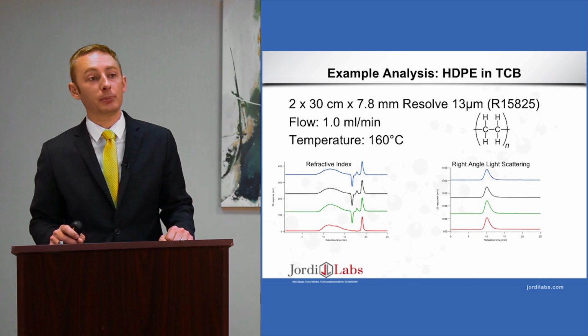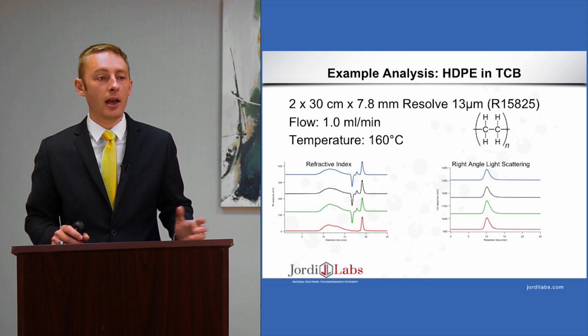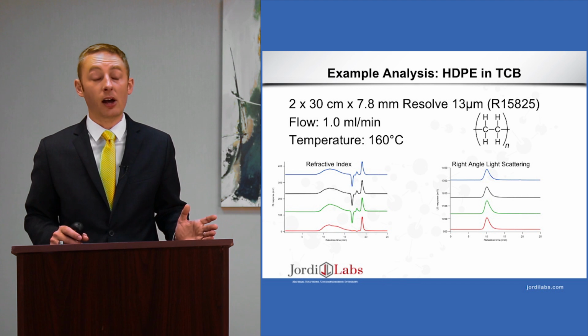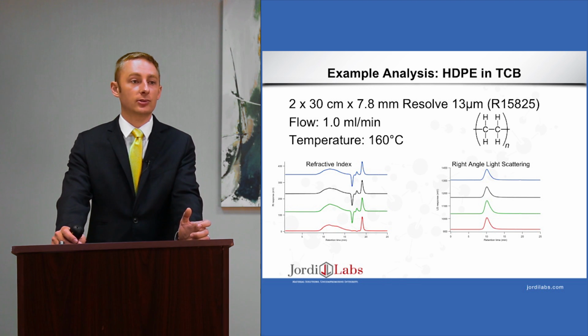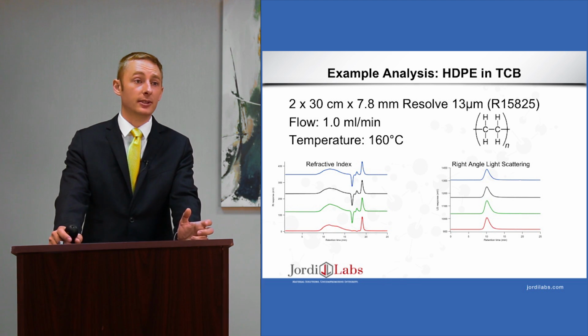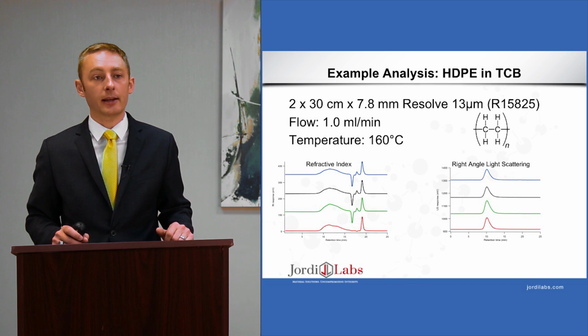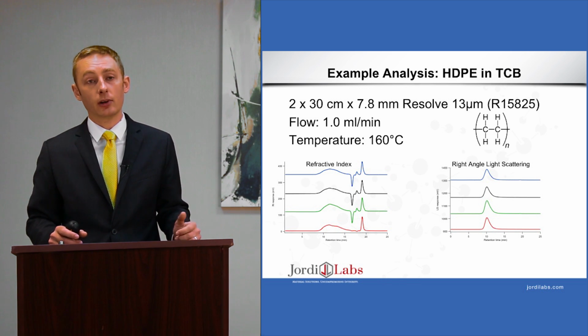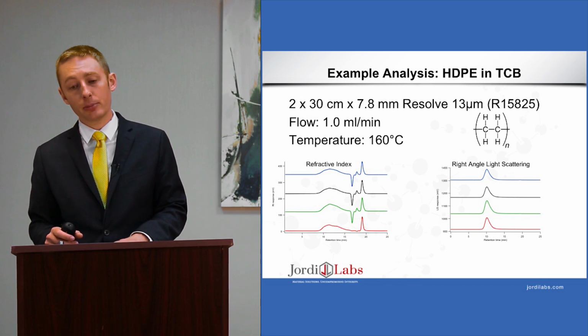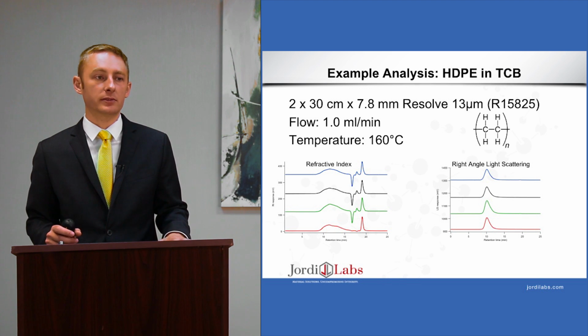Here we have high density polyethylene using very similar conditions, and you can see in this case it's at 160 degrees Celsius, so this certainly classifies as high temperature GPC. And we have, like I mentioned, several instruments which are dedicated to not only high temperature GPC, also specialty solvents.